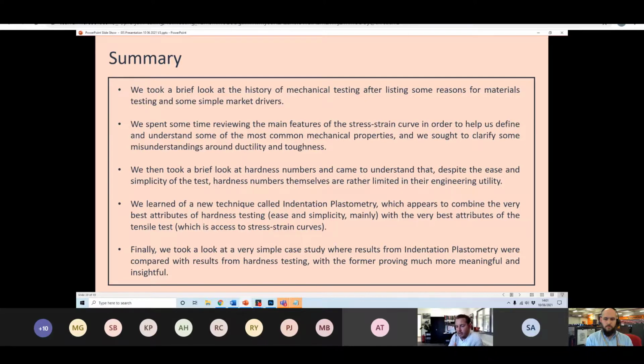Okay, so how do we go? What's the process to get from unknown material properties to known material properties through this profile shape? Okay, so it's an inverse finite element technique, and that's a standard methodology. It's very robust, and in fact we published a lot on this in the past. But if you want to know a little bit more about the underlying mathematical methodology, as far as I can say, so as not to release any intellectual property, we implement in our software package just a very bog standard FE approach with a continuum-based plasticity equation. It could be one of any number, Voce or Ramberg-Osgood or Ludwik-Hollomon or others, whatever.